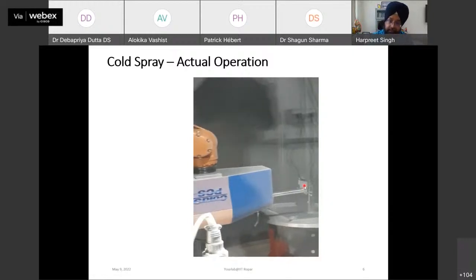Now, conventionally, this cold spray has been used for depositing small, thin coatings of the order of, say, a few microns, or sometimes even 1 mm and so on. But then people thought, why not keep on depositing material layer by layer? And that is where the idea of using this surface engineering technology for additive manufacturing emerged, right? So what would happen if I don't stop depositing after, say, 2 or 3 layers? If I keep on depositing layer by layer, I can achieve much thicker deposits here, and then I can take those deposits from this substrate and use them as a standalone geometry.